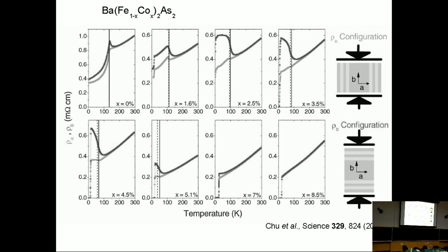A very interesting aspect of the system is what we call nematicity, and it is found below the magnetic ordering temperature. Mostly you have this orthorhombic distortion, and however, you have domains, orthorhombic domains, which are randomly oriented in a single crystal with equal occupancy of domains.